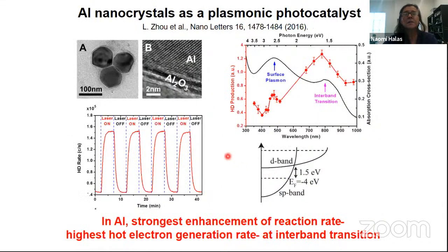So we tried to do that same experiment that I showed you with gold, basically dissociation of H2. We tried to do that with aluminum, and very much to our surprise, it worked very well. And why would it be surprising? Well, first of all, we don't have a clean aluminum surface. We have this thin layer of oxide that terminates the aluminum nanoparticle. But this layer is porous enough that it lets H2 through the layer, which is about 2 nanometers, and is able to interact with the surface.